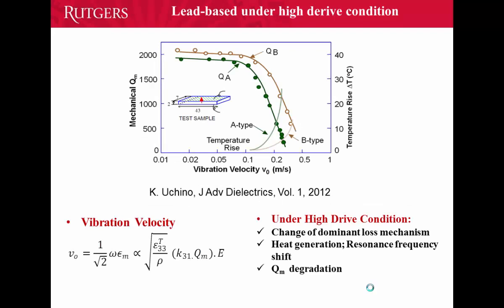The figure of merit for high power application is vibration velocity, which is the angular resonance frequency and maximum displacement under electric field, and is proportional to the electric field, mechanical quality factor, coupling coefficient, permittivity, as well as density. In this plot, you can see that the mechanical quality factor rapidly decreases after 0.1 vibration velocity, accompanied by heat generation and a shift in the resonance frequency, which is not favorable in high-power